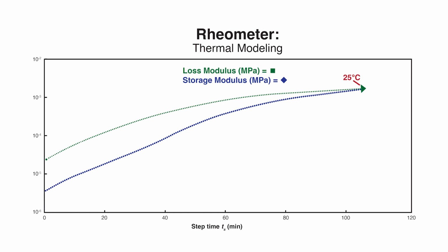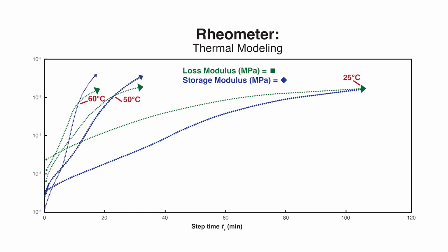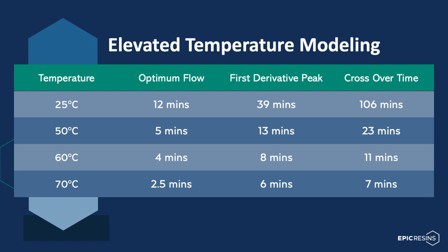Now, the question you have all been waiting for. How can we speed up our process? The rheometer also has the ability to model all of the above data at elevated temperature. This graph shows the same thermoset cured at 4 different temperatures. As you can see in the graph, higher temperatures yield shorter time to the crossover point. This table summarizes the time for each temperature to attain optimum flow, first derivative peak, and crossover time.